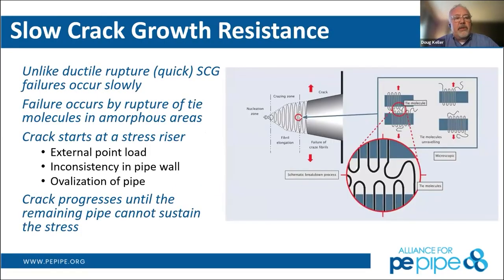So very briefly about slow crack growth resistance. What happens is if you get some type of a load imparted upon the pipe, some type of a point load, maybe it's put down on a rock, maybe there's a deep scratch on the pipe, what will happen is with the internal pressure, you will start to open up a crack. So that crack is growing from the inside of the pipe, which is that vertical line represents the inside wall